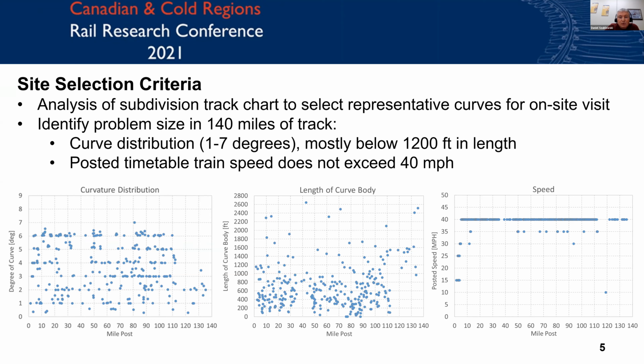Most of the curves were below 1,200 feet in length. Some of them were upwards of 2,600 feet, but those were the seldom cases. Most of them were quite lower. And the posted timetable train speed for that line was 40 miles an hour, but that's the posted timetable speed. That does not mean this is the speed that the trains go at all the time, and probably in fact they don't, but we went with that number for the assessment of super elevation, and I'll show you those results in a minute. So those were the first things that we looked at.